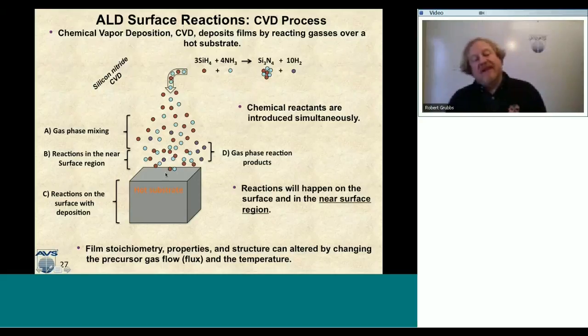And what we can do with CVD is change the film stoichiometry by putting a lot more of one gas in than another. We can change the properties of the film, the structure, all by just changing the reactive precursor flow of each of the individual reactants. And that would be essentially the flux. And we can also change the structure and properties of the film by changing the temperature. I'm giving you this silicon nitride example here. This is the stoichiometry of the silicon nitride. It's the chemical equation. Notice that we give off 10 hydrogen atoms per mole of the silicon nitride being formed. And by doing so, if our reaction temperature isn't hot enough, we will include a lot of this hydrogen in the film. So the CVD of silicon nitride typically happens at a much higher temperature.